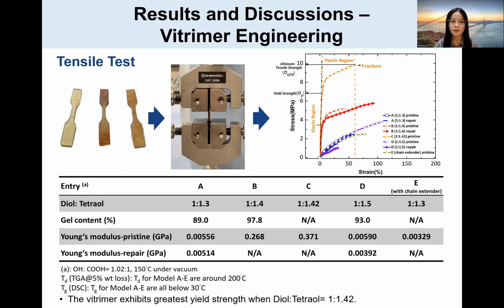So, to be repairable, there must be excess hydroxyl groups to perform transesterification under high temperature. And to be rigid, the ratio of OH groups from diol, which is the degraded product, to tetraol, the cross-link agent, matters. The cross-link agent will make the vitrimer rigid. The ratio of diol to tetraol is really critical.